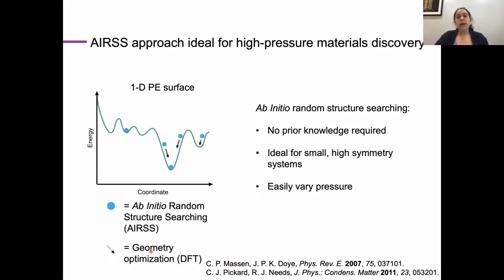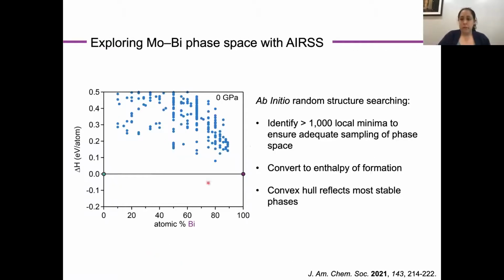And so I applied this approach to my molybdenum bismuth system of interest, and here I'm showing you my results from 0 GPa. I identified over 1,000 converged structures, each corresponding to local minima on the potential energy surface. To compare those structures relative to each other, I looked at their enthalpies of formation and plotted all that information on this diagram here, in which I have formation enthalpy on the y-axis, composition on the x-axis. We're moving from molybdenum on the left to bismuth on the right.